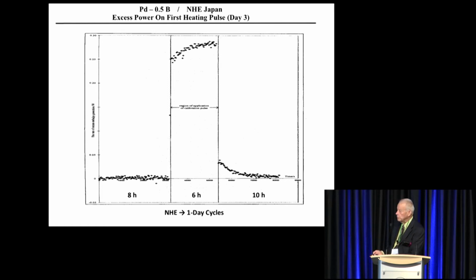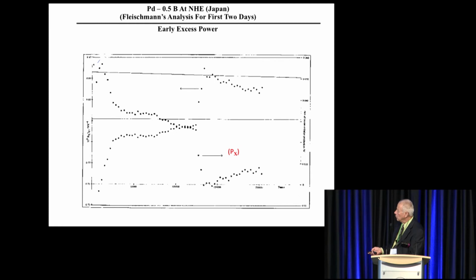And it actually comes earlier than that if you look at this graph, but Martin doesn't make his graphs easy to follow, and the numbers are not easy to read. But this is the heat of loading right up here. This is the maximum loading you should have gotten. You shouldn't have gotten any more than this based on the enthalpy of loading. But right off the start, you have excess heat due to something more than you would expect from loading, and then gradually it goes away and almost to zero.